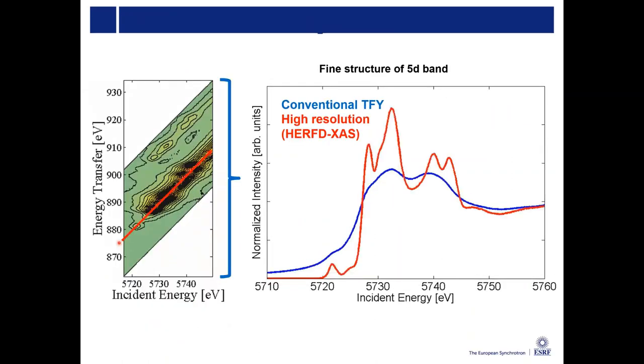What I can do now, I can take a diagonal cut through this two-dimensional energy distribution. And I get this red line here, which is called a high energy resolution fluorescence detected X-ray absorption spectrum. And I can compare this to a conventional absorption spectrum that I would measure, for example, in transmission mode or total fluorescence yield. And you see that this diagonal cut, this kind of RIXS technique, allows you to improve your spectral resolution enormously. So I get a spectral broadening in principle that is not limited anymore by the lifetime broadening of my intermediate state.